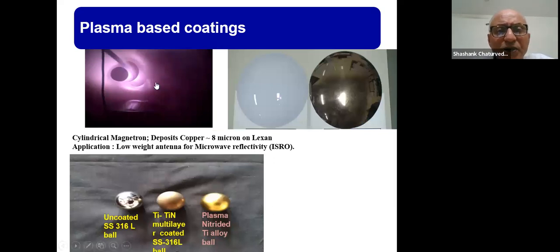You can use plasmas to produce coatings of different types. For example, there was one requirement from ISRO where they wanted to make a lightweight antenna for microwaves. We managed that by taking Lexan and producing a very thin coating, just an 8 micron copper coating. So it produced a lightweight antenna.